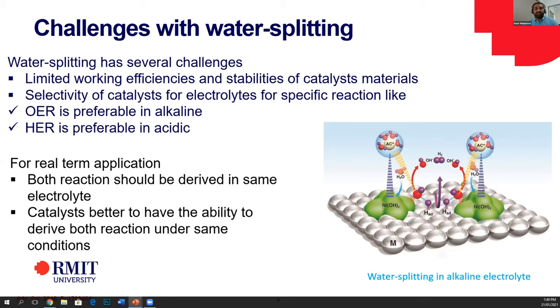Or at least, even if we have two different electrolytes, they can do the catalysis in the same medium. But most of the OER catalysts are not stable in acid, and most of the HER catalysts are not stable in alkaline medium. That's the main issue that we need to overcome. Secondly, we are mainly using fresh water, and fresh water is only 3 to 4% of the total water available. If we use that small amount of water to produce hydrogen, then how will we survive? What will we drink? So we have to shift from fresh water to sea water. That is another hurdle because there are a lot of salts in the water, and a lot of biological life, microbes and bacteria, which cause a lot of problems. These are some of the issues with water splitting that we need to overcome.